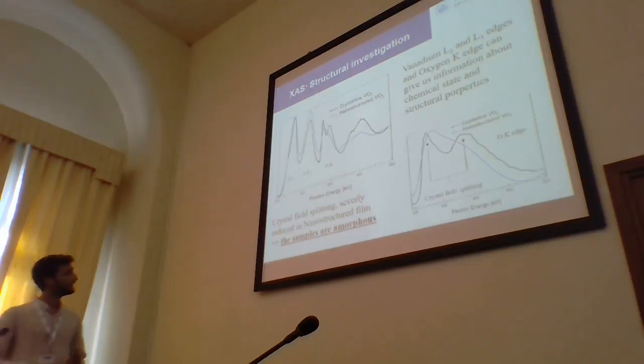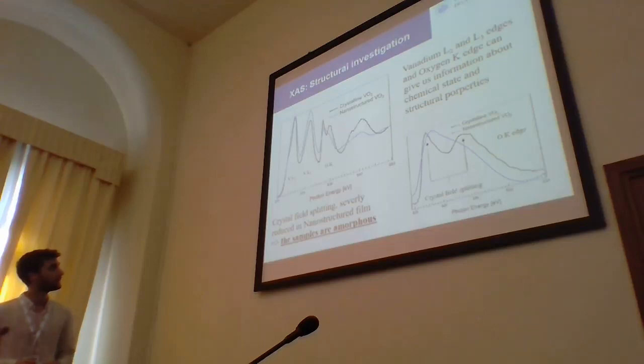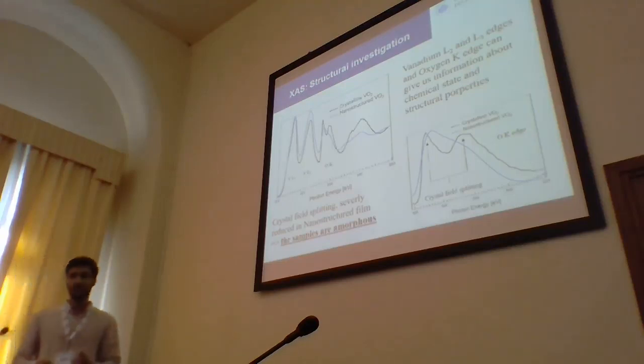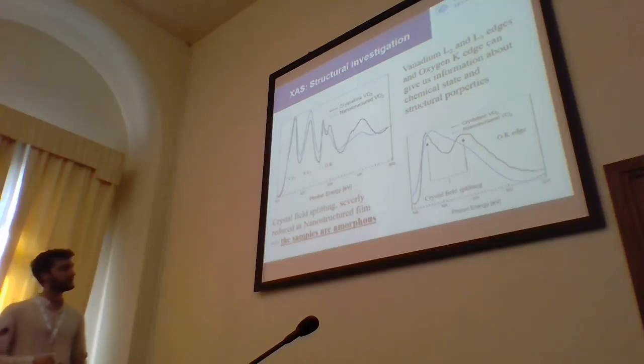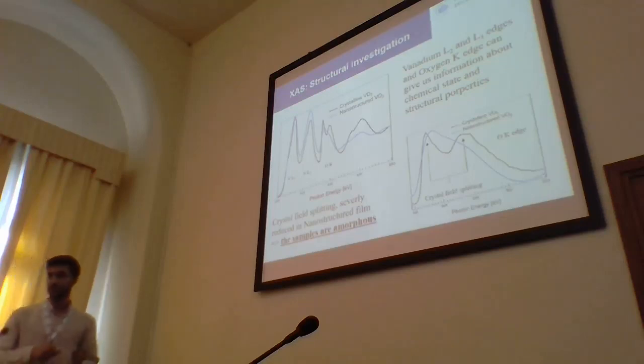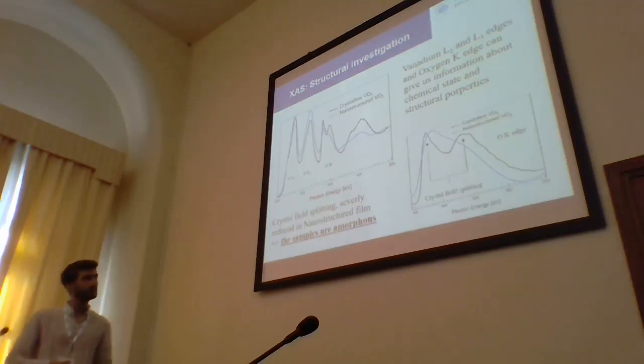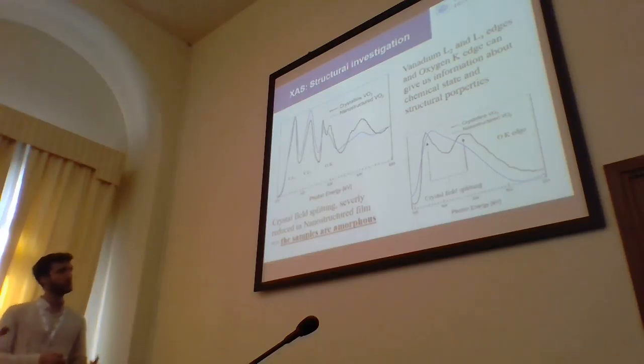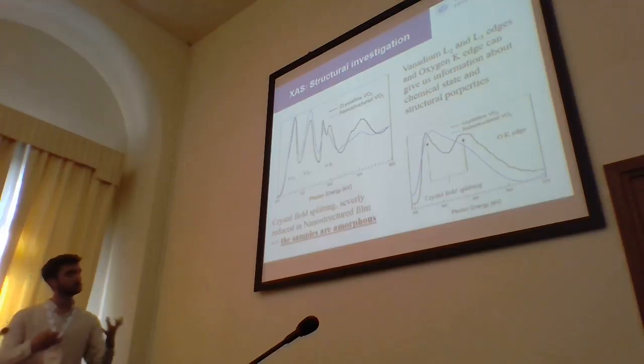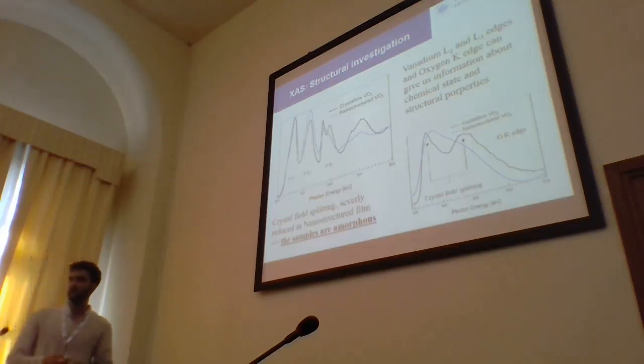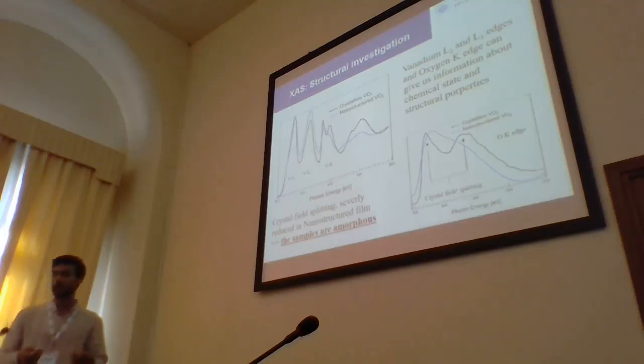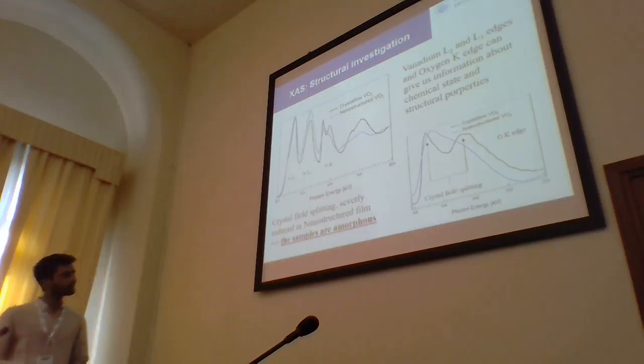Again, in vanadium oxides in general, we have vanadium L edges and oxygen K edges very close, which means that the vanadium 2p electron and the oxygen 1s electron are very close in binding energy. Studying a crystalline sample of vanadium dioxide, on the oxygen K edge, we can see a very nice crystal field splitting, which results in two features in the pre-edge of the oxygen K edge. While in the sample I produced with the cluster source, we have a wide bump, which means that the crystal field is not strong enough to have an ordered sample. So in the last analysis, our samples are amorphous.